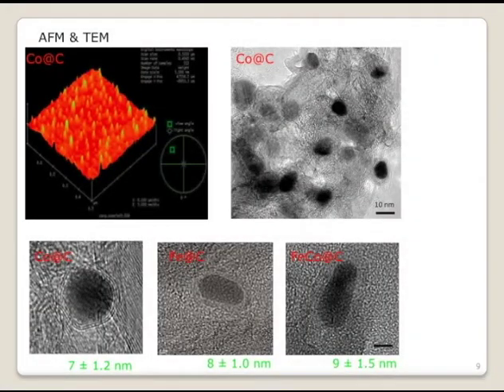Let's see. These are the atomic force microscope and the TEM images. It's the AFM. You can see the particle, this dot. The first image is a carbon-coated cobalt particle. You can see a lot of particles are coated with a carbon shell. From the TEM image, we can tell the cobalt particle size is around 7 nanometers. This is an iron particle. It's 8 nanometers. The iron cobalt alloy is around 9 nanometers. They're all well protected by the graphitic layer. The layer is about 2 to 7 layers of graphitic material, carbon layers.